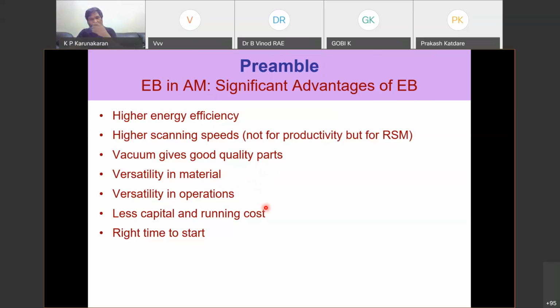Electron beam will not find applications as of now in the current technology for non-metals because it requires conduction. But you don't know, in future, they may come up with electron beam, which can also penetrate non-conducting materials. Because in the beginning, people used to keep the table as 0 and the cathode was kept at minus 60 kV or minus 80 or even minus 120 kV. But today there is an anode in the gun itself. Okay, so the beam generation happens within the gun, the complete beam generation, focusing, deflection. So you get a clean beam coming out and hitting the target. So the potential difference between the anode in the gun and the table is not substantial.